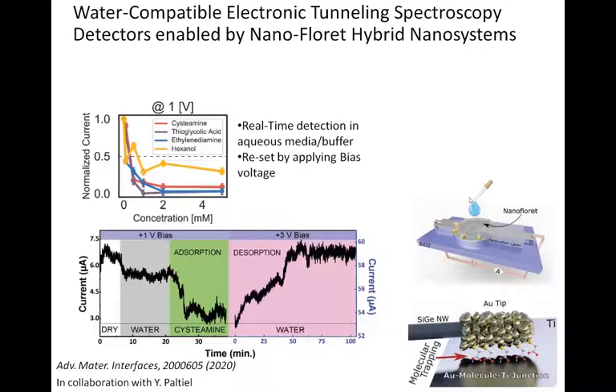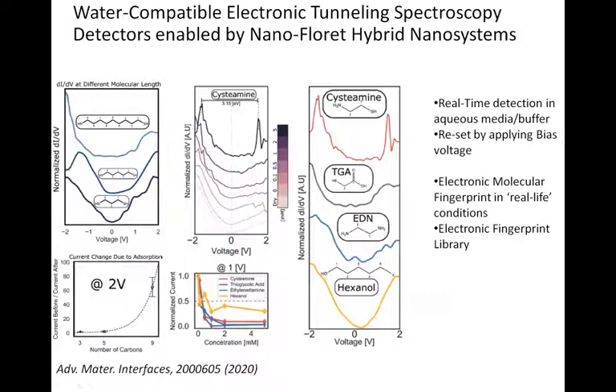But the really interesting stuff comes here. This is what I showed you, using this in aqueous solutions, in buffers, or in organic media, it doesn't really matter. You can get band gap evolution of the IDV curve as a function of chain length, and you can see here the fit. Furthermore, for different molecules, not only do you see the decrease in current, but at each data point, you can really take the IDV spectrum, and you can see how the IDV data evolves with concentration. And this is already fingerprint detection of the normalized dI/dV curves for different analytes.